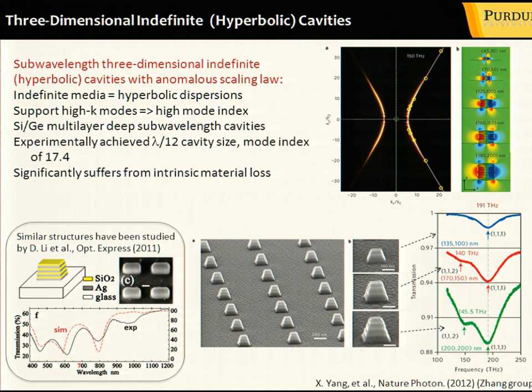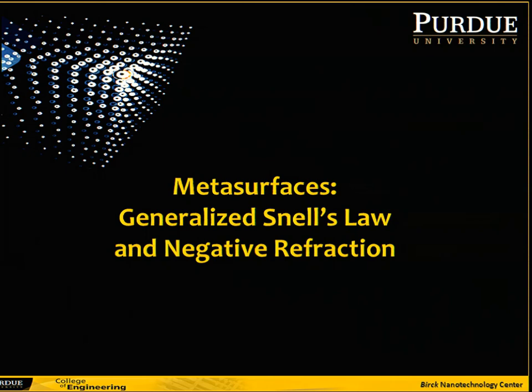This is recent work done by Shang Zheng, where he used cavities based on hyperbolic metamaterials. And again, because in hyperbolic metamaterials there are propagating modes with very large Ks, they were able to make cavities which are 12 times smaller than the wavelength and can still support a cavity mode, which basically means that the effective refractive index in these structures could be very large, in this particular case like 17. That demonstrates that with hyperbolic metamaterials, you indeed can go deeply beyond the diffraction limit.